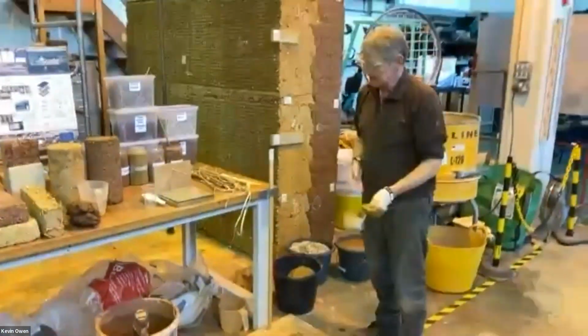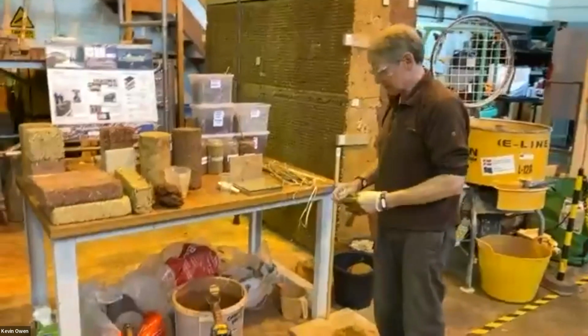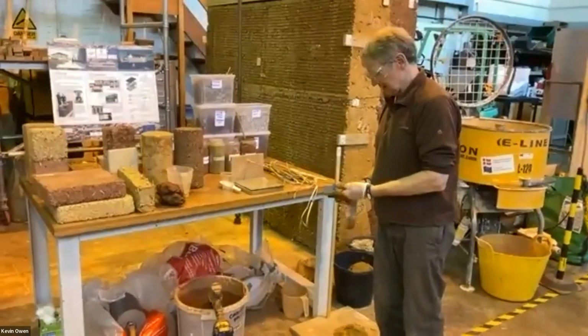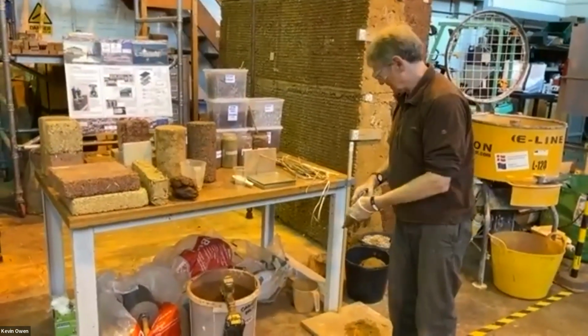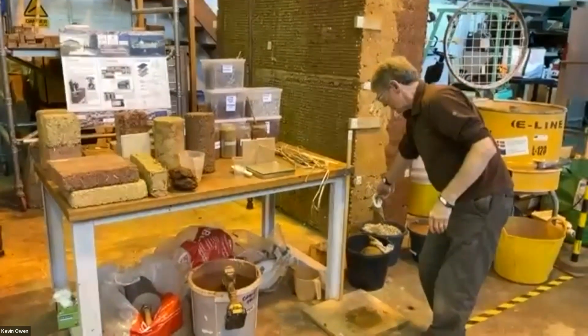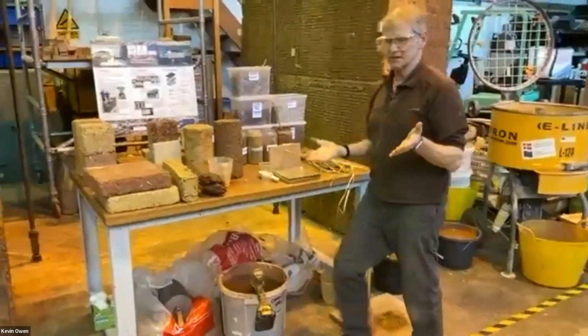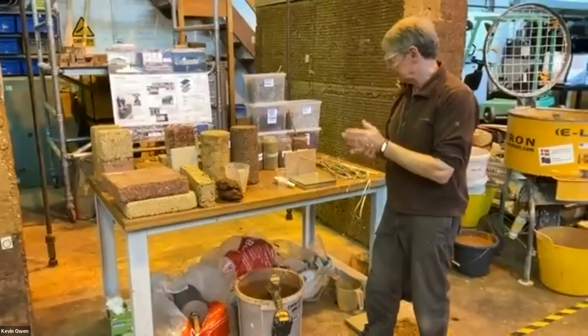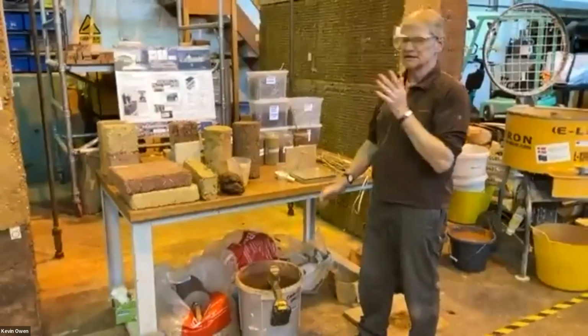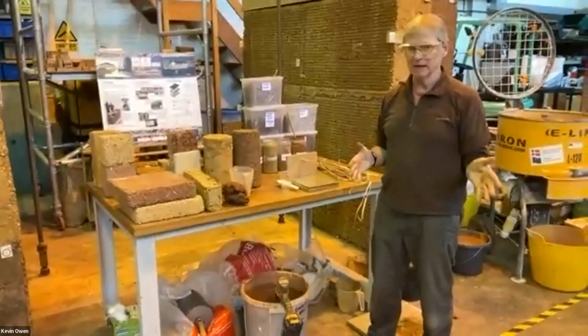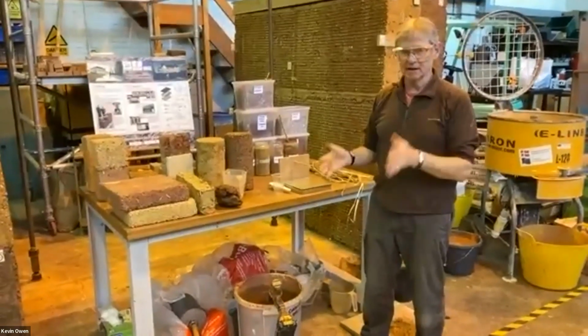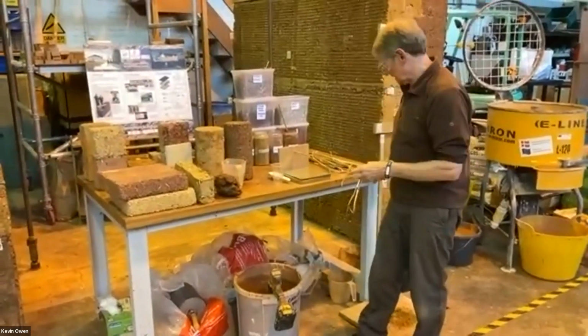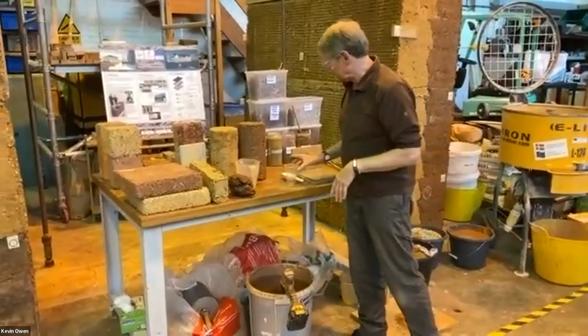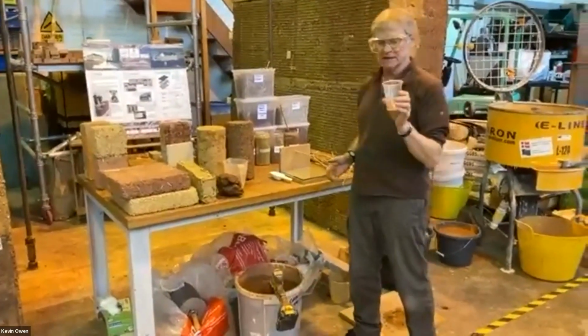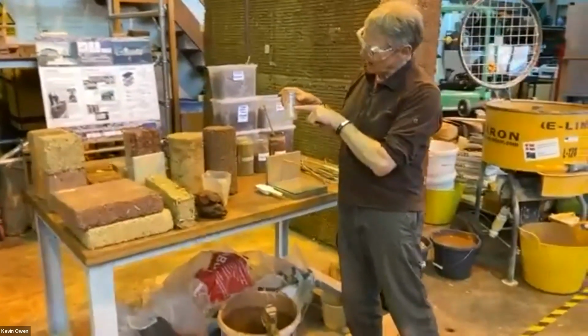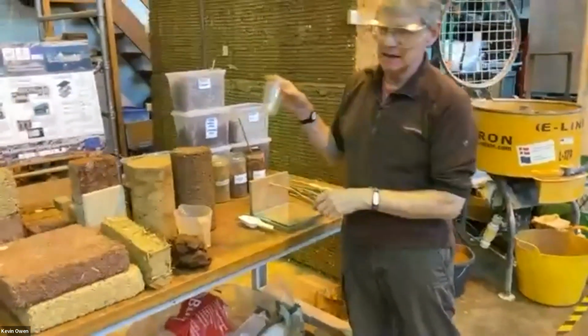Now we come to the other test we have, which is the puddle test, or viscosity test. And again, it's a very simple method. And the guys on site, when they were building our building, meticulously measured this every day. So they'd make a mix up the night before, and then they come back and check that the viscosity had not changed. And to do this, all you need is a plastic cup with a little mark on it at 100 millilitres